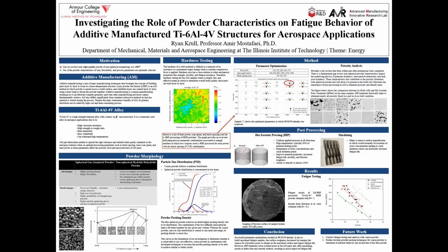Machining is also quite important as a supplementation to HIP, as it smooths and removes surface imperfections. Surface roughness is also another high stress concentration area, as the roughness can be seen as tiny cracks where stress is high and damage occurs first, as those tiny cracks then grow and propagate throughout the structure. By smoothing the finish as much as possible, this improves fatigue life and part life cycle.